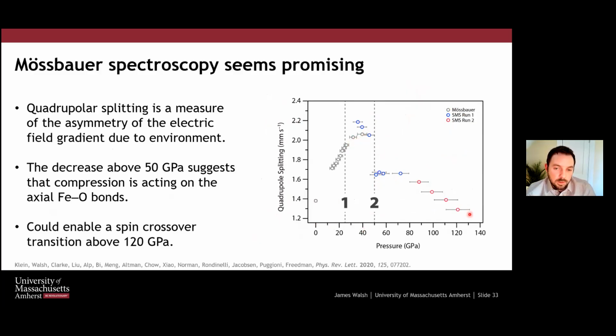And so what we see is an increase with the initial compression, and then a discontinuity, and then a decrease. And so this is consistent with what we've seen from the single crystal data, that up to 30 GPa, we're just compressing the equatorial bonds and not the axial ones. So it's a tetragonal elongation because we're not compressing those axial bonds. And so we're increasing the asymmetry and therefore increasing the quadrupole splitting.